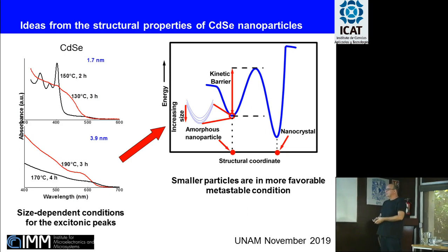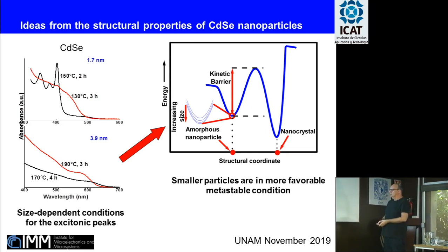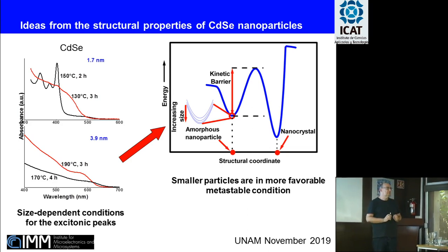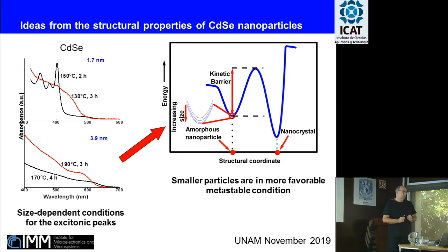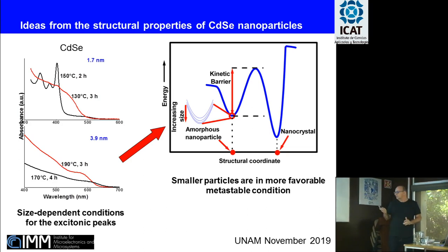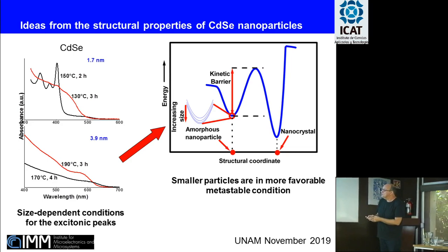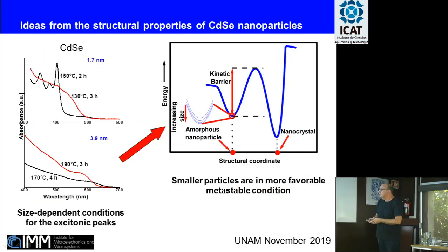During the course of this study, what we observed was that we could obtain the crystallization of amorphous cadmium selenide nanoparticles depending on the size of this nanoparticle. Smaller nanoparticles were more easily crystallized. You needed to heat them at 150 degrees, for instance, for 2 hours when they were 1.7 nanometers, while when they were much larger, something like 3.9 nanometers, we needed 190 degrees C for 3 hours. So the smaller the particles, the easier the crystallization.